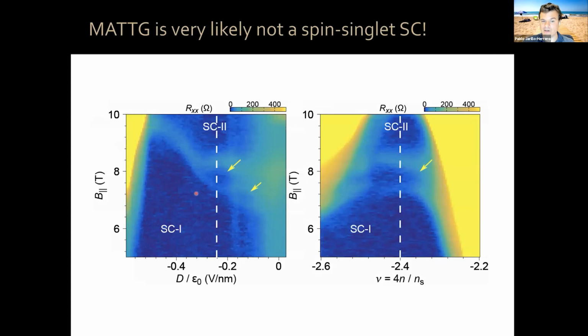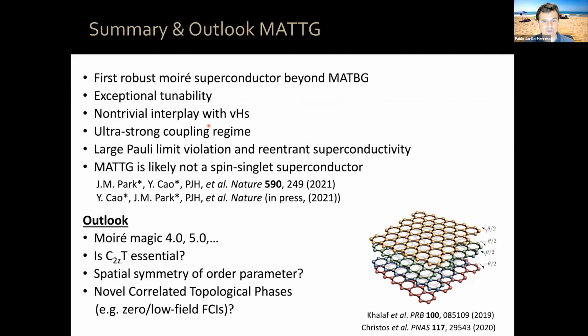So it's very likely that magic angle twisted trilayer graphene, where we can realize a similar type of transition between two regions, okay? With a low field region, and a reentrant region at high magnetic field. This is also related to not spin singlet superconductivity, either spin triplet or linear superpositions of spin singlet and spin triplet superconductivity, okay? So with this, because my time is up, I want to end.